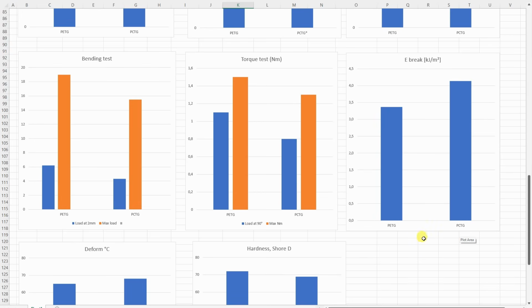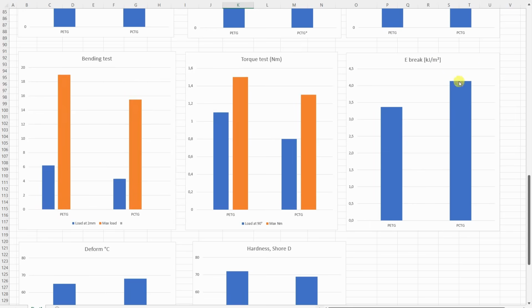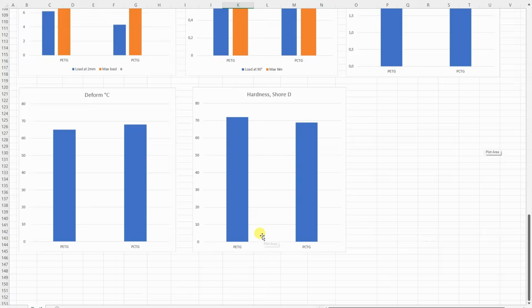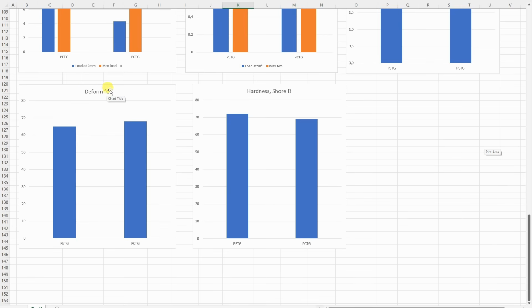Now this is the result of the Izod impact test, and here I was very disappointed with PCTG because according to specifications it should have breaking energy up to 90 kilojoules per square meter, but as you can see this is a little bit more than 4. Yes, it is stronger than PETG, maybe 15 or 20%, but the difference should be at least, I don't know, 10 times stronger.